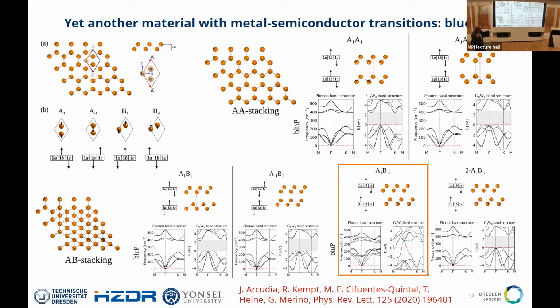And then you can actually look at them as a little mathematical problem. You find 7 structures, and we find 6 structures, as the 7th one has two local minima. You can calculate everything, and what you figure out is something very remarkable. The most stable bilayer is, contrary to the monolayer, metallic. That's weird. So that's also what the people at PRL thought. And I mean, it's really crazy, and let's hope that we can get that realized experimentally very soon.